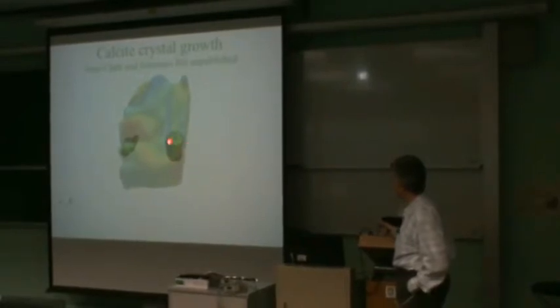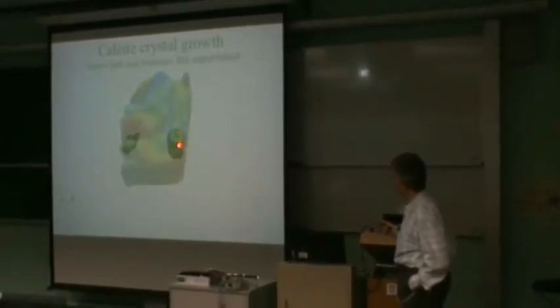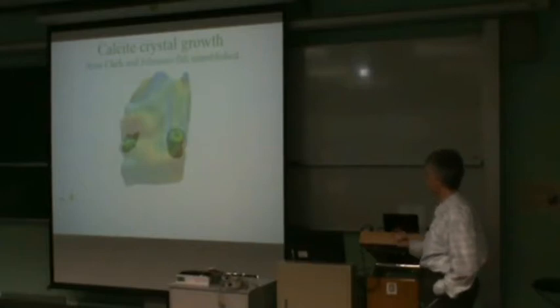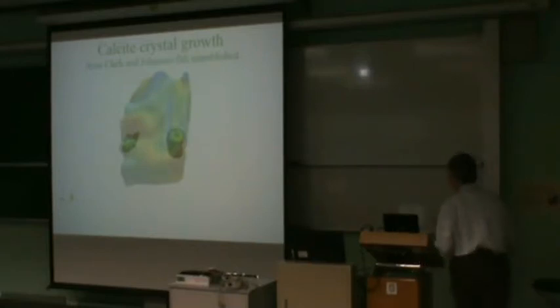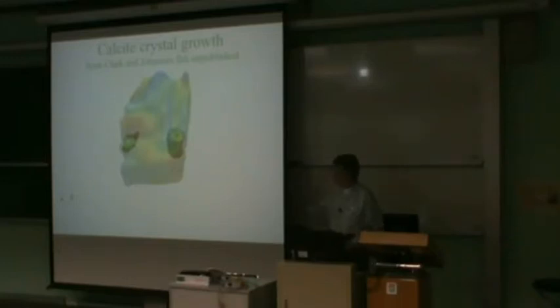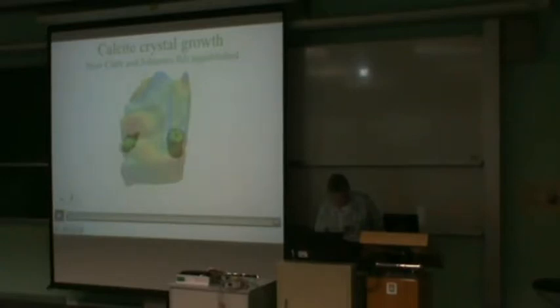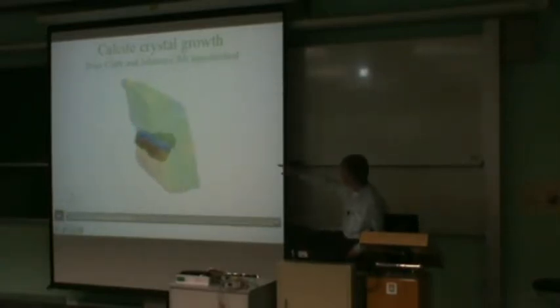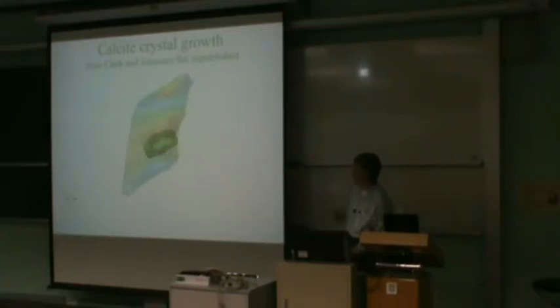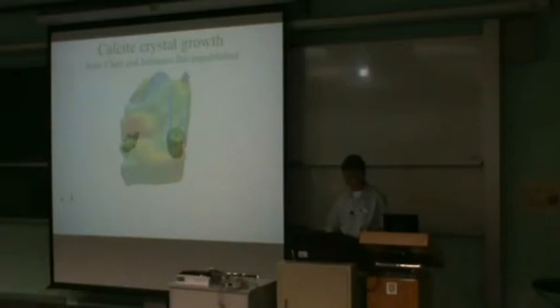So what Jesse has done to project this is he's faded out the block of the crystal itself and located the dislocation line. This is a screw dislocation that's going through the crystal. He's located the line, drawn a circle around it, and shown the phase on the surface of that cylindrical tube that is surrounding the dislocation. And if you look at it closely, and I'll have to play the movie again, you'll see that the phase wraps around by 2 pi as you go around that loop. So we've got a classical screw dislocation. You can see the cut plane of the wrapping of the projection of the phase just on the outside there.